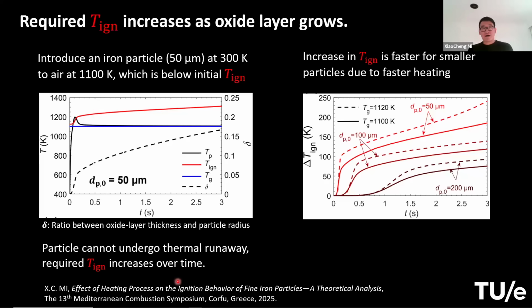And in this graph, I summarize it with two comparisons. One is the size dependence. You can see that this increase in required ignition temperature builds up faster for smaller particles. These curves on top are for smaller particles. This is easy to understand because smaller particles can be heated up faster, so higher temperature leads to higher oxide layer growth.